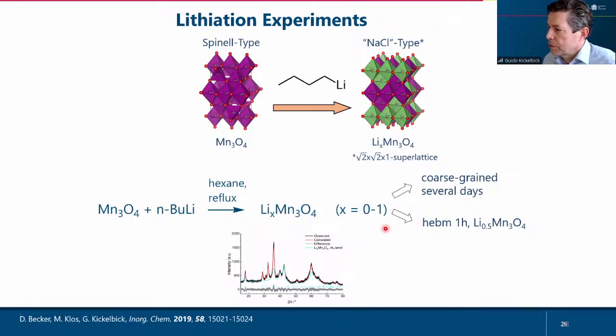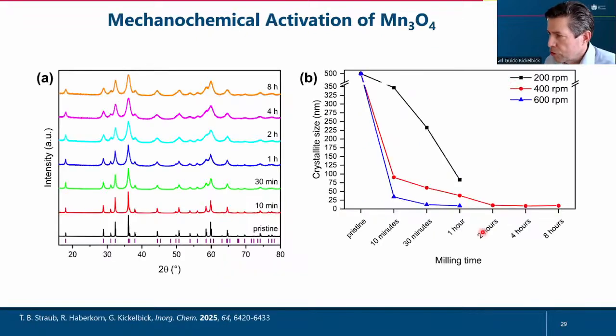And here you see already the result. If you have the usual material, the coarse-grained materials, you need several days to lithiate that. With the material from the mill, you get after 1 hour 50% lithium intercalation, which is a very interesting result for potential battery applications. And we again could prove that this activation, as I have shown you already in one of the first slides, can be done after 10 minutes. This is nearly long enough to do this activation. And then if you mill longer, this seems not to have a similar effect.